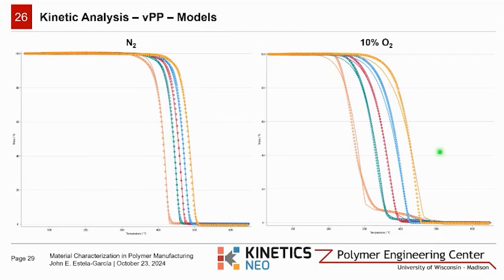And the current model that best captures the oxygen environment data actually consists of 6 reaction steps. And the model is based on the assumption that the thermal oxidative degradation of polypropylene occurs with a change in the decomposition of radicals to degradation to random scission. So as these polymer chains start degrading, they're forming different products. They're forming waxes, they're forming oils, and all of these are then continuously degraded until you end up with gases. We can see it has a very good fit with our experimental data.